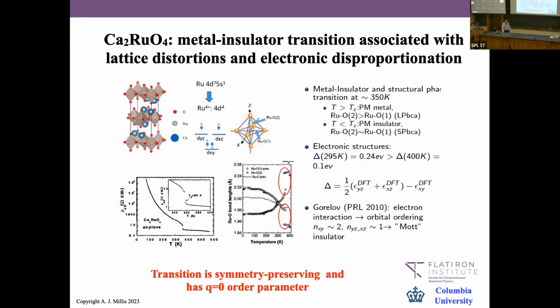Anyway, this material has a high temperature metal to low temperature insulator transition. You can see here an electrical resistance versus temperature: high temperature, more or less weakly temperature independent, relatively small resistance; low temperature, rapidly rising resistance, with a transition in between. This is associated with a noticeable change in the crystal structure.